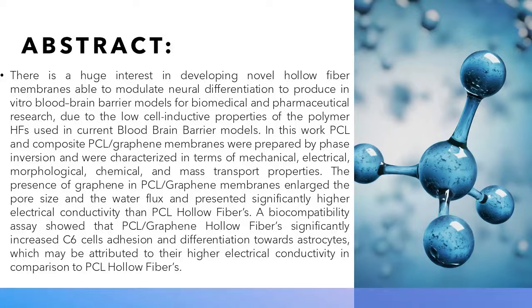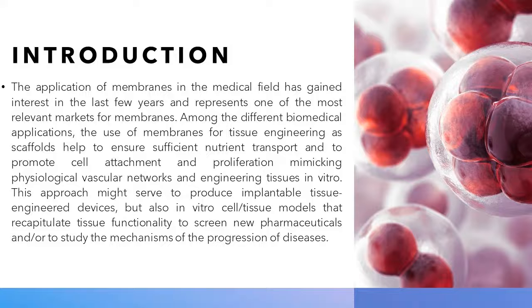The presence of graphene in PCL graphene membranes enlarged the pore size and the water flux and presented significantly higher electrical conductivity than PCL hollow fibers. A biocompatibility assay showed that PCL graphene hollow fibers significantly increase C6 cell adhesion and differentiation towards astrocytes, which may be attributed to their higher electrical conductivity in comparison to PCL hollow fibers.